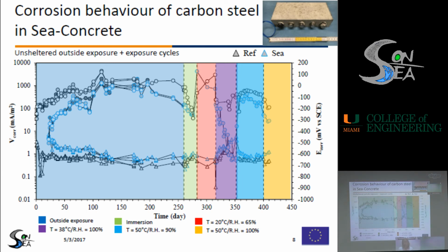The blue symbols represent the behavior of a carbon steel bar embedded in sea concrete, so concrete made with seawater. We can observe that both the corrosion potential and the corrosion rate were a little bit different from those measured in the carbon steel bar embedded in the reference, indicating that the behavior was slightly different. But what we can observe is that in some conditions, in particular when the temperature was high and the relative humidity was high too, there was a drop of the corrosion potential and an increase of the corrosion rate, which indicates the occurrence of corrosion during this exposure condition.